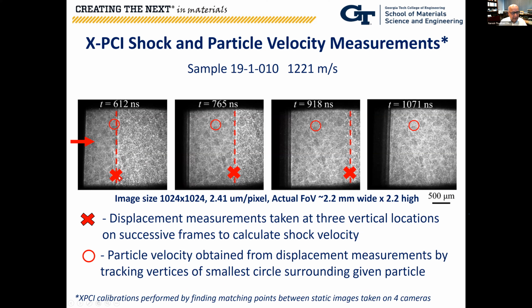What we did is identify 3 locations along the vertical span of that shock front at each of these 3 times. At the 4th time, the shock front is past the sample. By monitoring the time of travel and the distance of the displacement, we get the measure of the shock speed of the material.